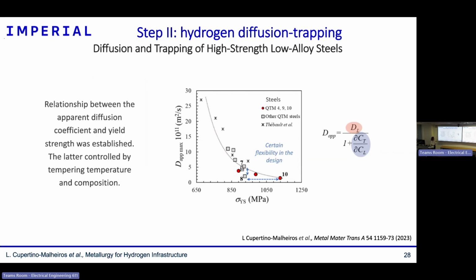All right, and it's what I have just said. And then one thing to notice is that this hydrogen diffusion kinetics here incorporates the two phenomena I said earlier: the diffusion coefficient at the lattice, that's DL here in pink, and also the trapping effect. And this trapping effect, this attraction of hydrogen to these structural features, basically depends on two parameters.